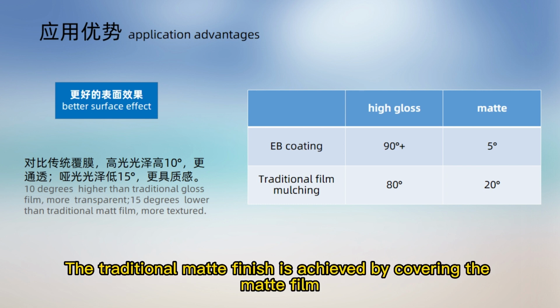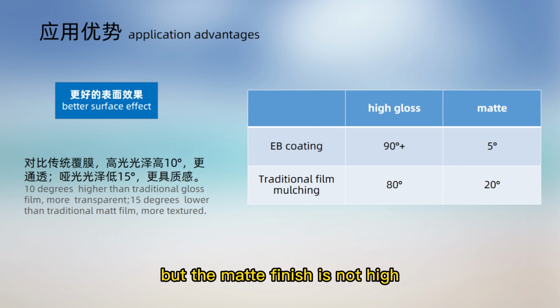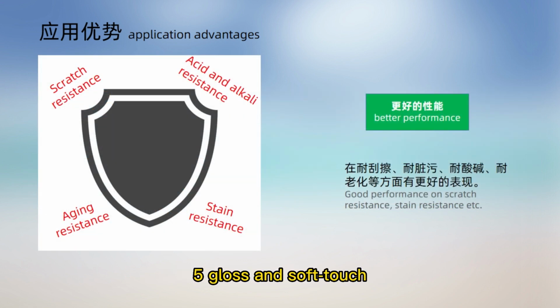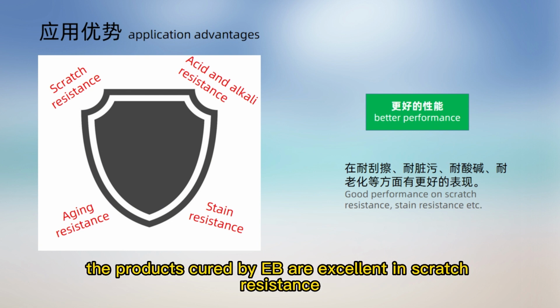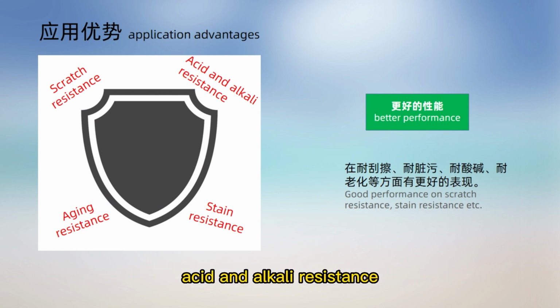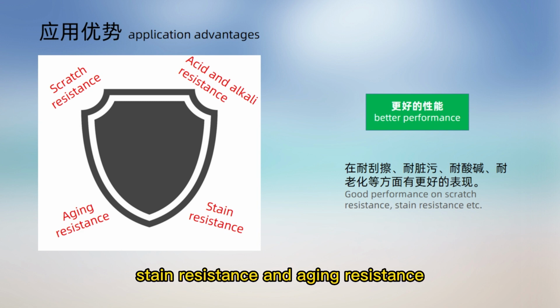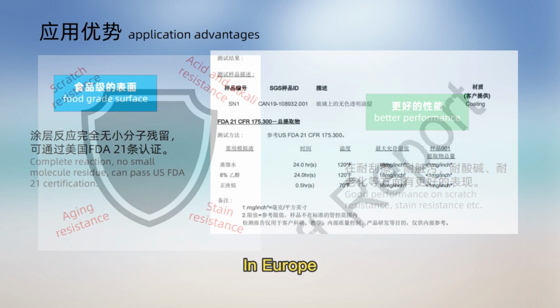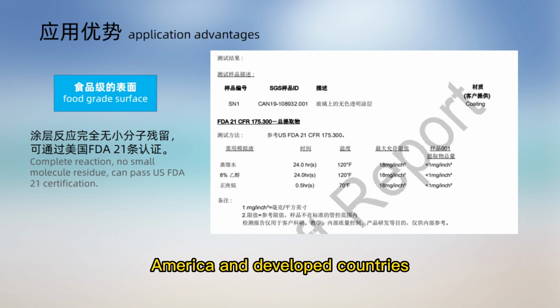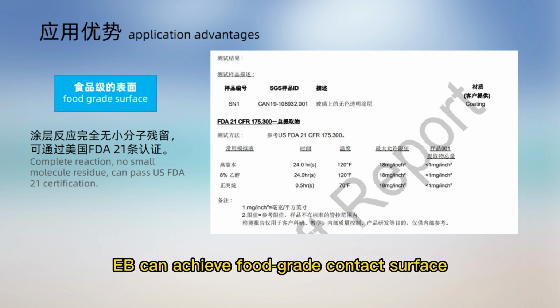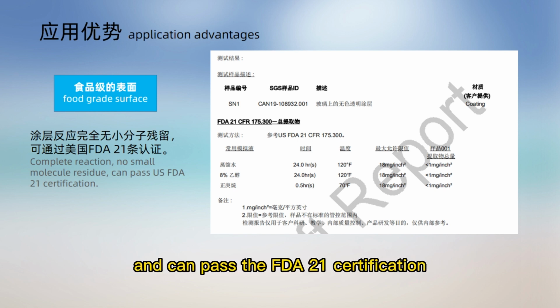The traditional matte finish is achieved by covering the matte film, but the matte finish is not high, only a dozen or 20 degrees. Through a special process, EB can achieve very low gloss, 5 gloss, and soft touch. At the same time, the products cured by EB are excellent in scratch resistance, acid and alkali resistance, stain resistance, and aging resistance.